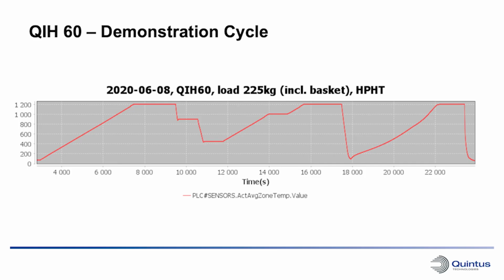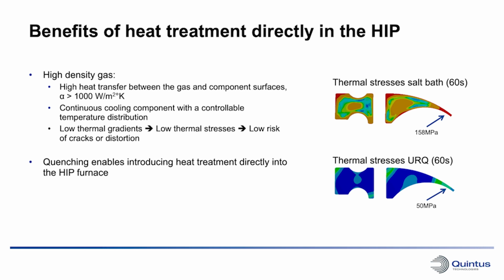Okay, can you steer stepwise the cooling rate as well, so we can stop at plateaus? Yes, of course. Since we cool the media, we are not putting the samples into a cool bath, for example. We cool the media at the same time, so that will also be very beneficial for the components. You will not get high stresses or large deformation because you have less thermal shock to the material. Okay, interesting. So being able to take a stepwise cooling profile, if you like. Can you do the same with heating, by the way? I mean, can you do the heating profiles upwards as well for specific materials? If it's required, yes, of course. It's pretty easy to program. Okay, and you can go up with pressure first, and you can heat it later. Yeah. So all these trials are possible then in the unit.